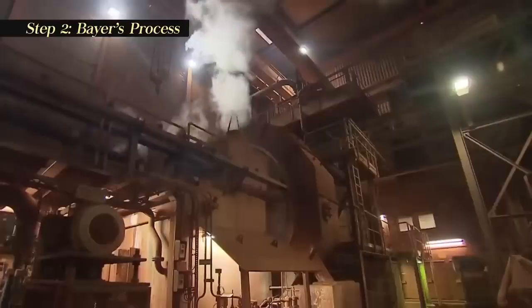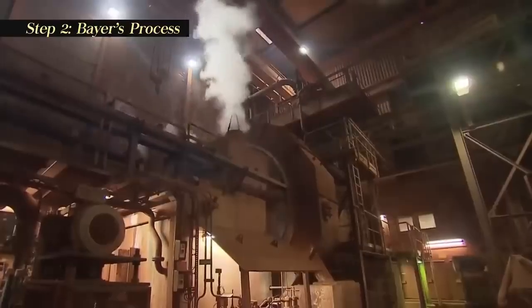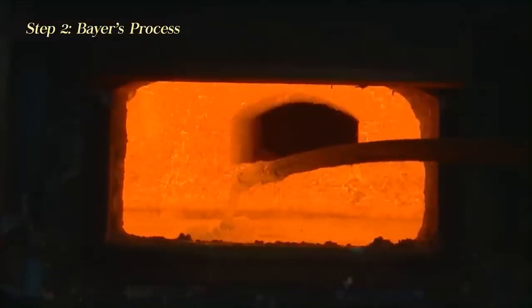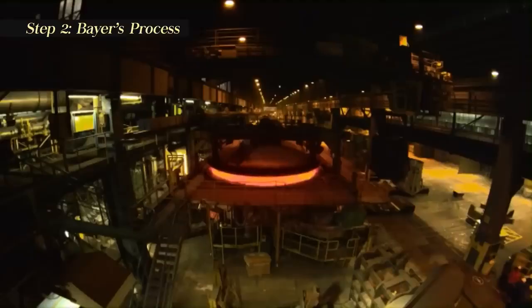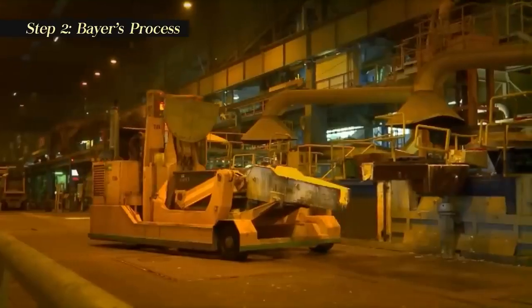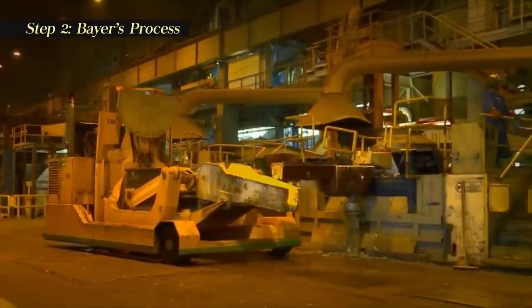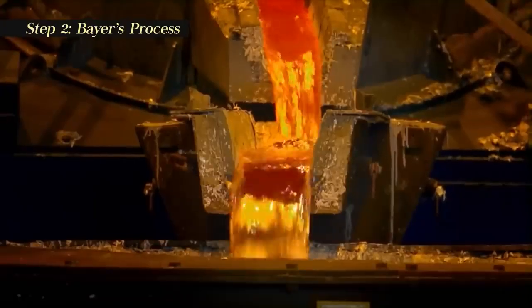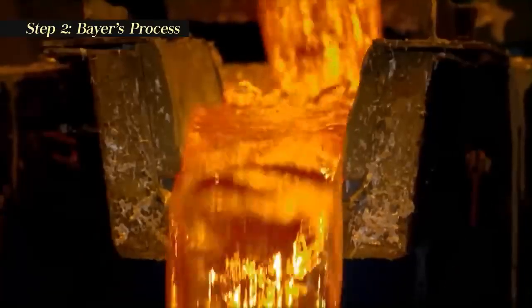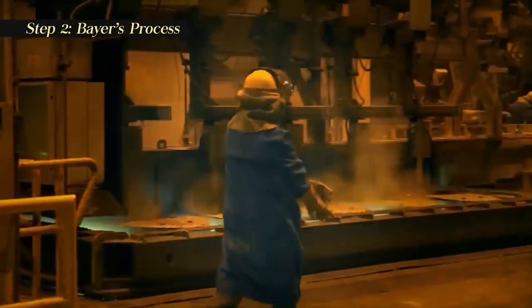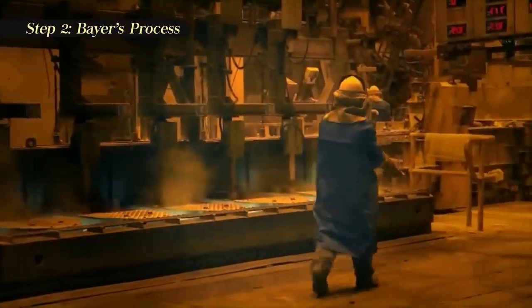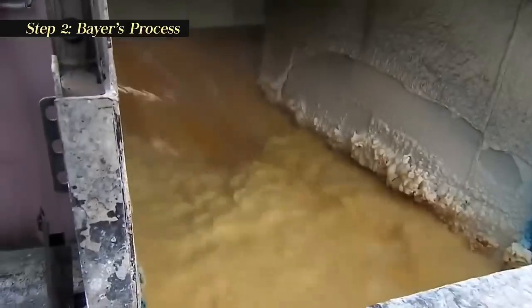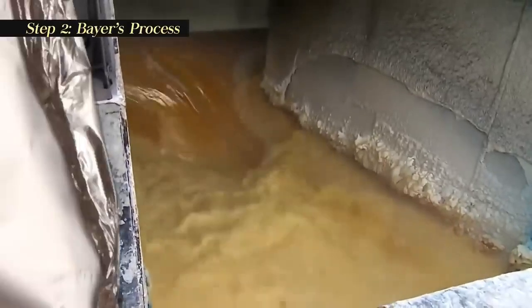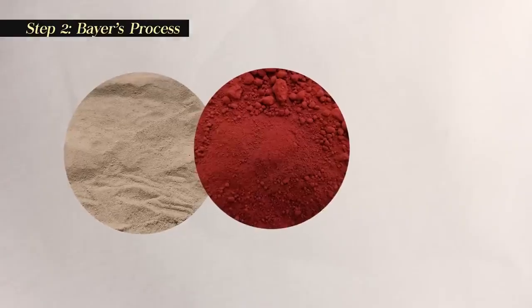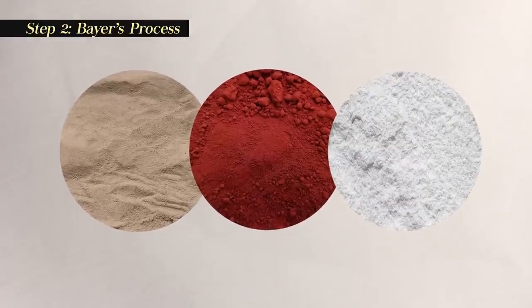Additional caustic soda may be added to ensure that all aluminum-containing compounds are dissolved. The hot slurry, which is now a sodium aluminate solution, passes through a series of flash tanks that reduce the pressure and recover heat that can be reused in the refining process. The slurry is pumped into a settling tank. As the slurry rests in the tank, impurities that will not dissolve in the caustic soda settle to the bottom of the vessel. The residue, called red mud, that accumulates in the bottom of the tank consists of fine sand, iron oxide, and oxides of trace elements like titanium.